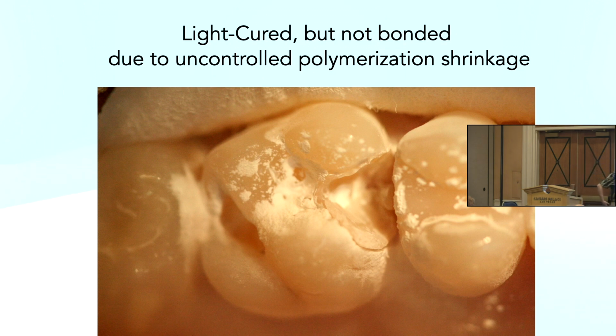I don't know if you can see this, but there's a composite that I was removing. I was doing it very slowly. Can you see the space there? That's because deep dentin bonds form more slowly. And when you use composite like amalgam, it's shrinking to itself. It's bonding to itself. So what's going to give first? The slowest bond to develop. And what's that bond? Deep dentin. So when you go back Monday morning and you're removing an old composite, do it slowly. See how many of these don't delaminate or haven't already delaminated.